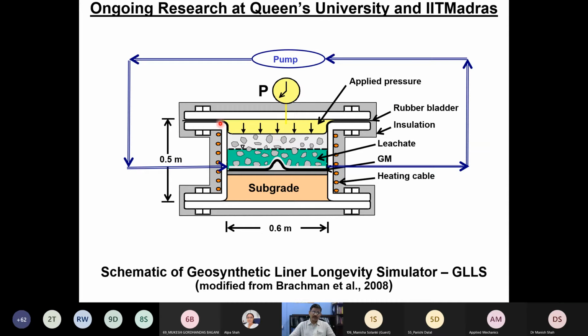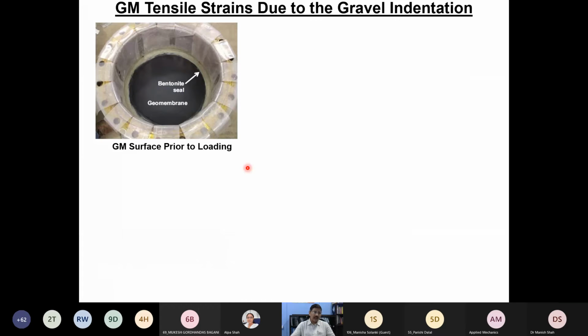To do that, a rubber membrane has been placed. By inflating the rubber membrane, we push the gravel particles downward, and as a result we can measure the level of overburden pressure acting on the membrane. This is the GLLS before loading. You see that the membrane is very smooth, and below there is a GCL. To seal that, we placed a bentonite seal, and these tiny holes 1, 2, 3 and 4, at more or less 45-degree angles, are the leachate recirculation units.